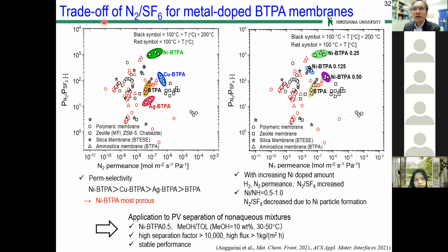This is the summary of the trade-off of nitrogen over SF6 as a function of nitrogen permeance. Nitrogen has a size of 3.6 angstrom, and SF6 5.5. So this is a good index to identify relatively large pores. These circles indicate BTPA doped with metal, and the other points are collected from papers on polymer or zeolite, etc. This is the type of metal, and this is the amount of nickel doping. As you can see, our metal-doped membrane shows very high selectivity of nitrogen over SF6, and also high permeance.